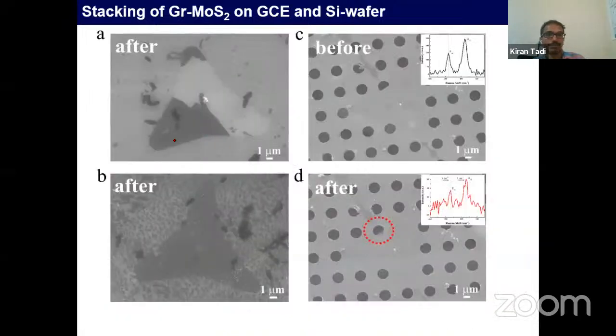Comparing with previous literature, we wanted to see whether ascorbic acid really disturbs the molecule, and we confirmed that where graphene is not present to protect the MoS2, it is etching the surface.